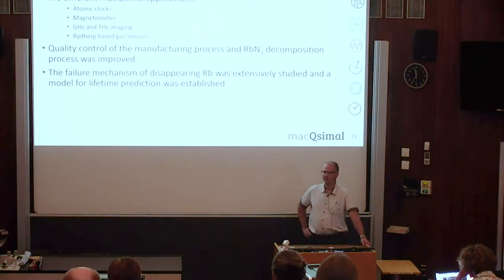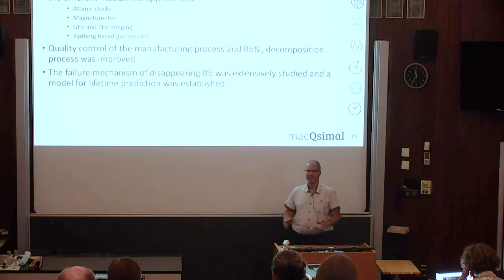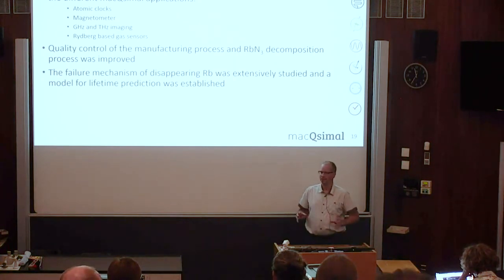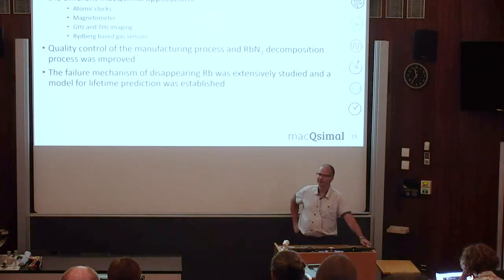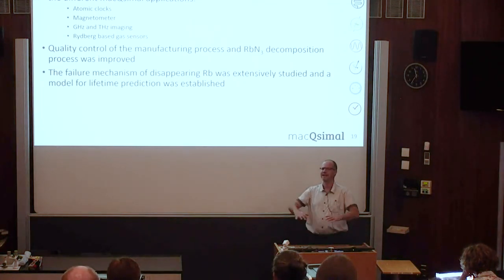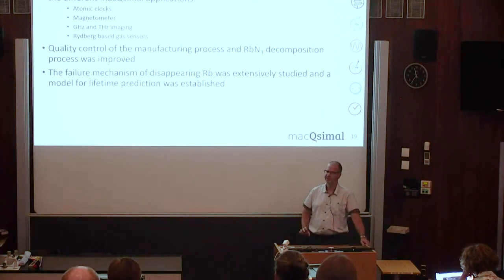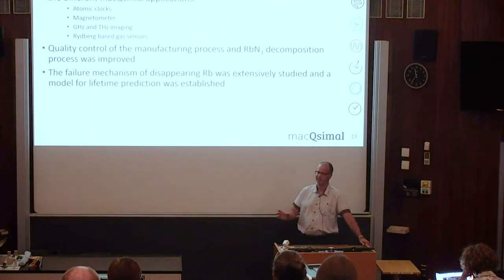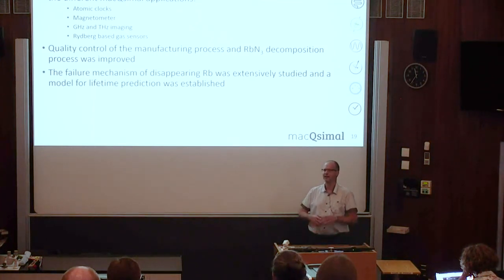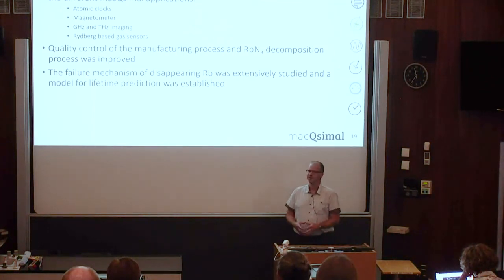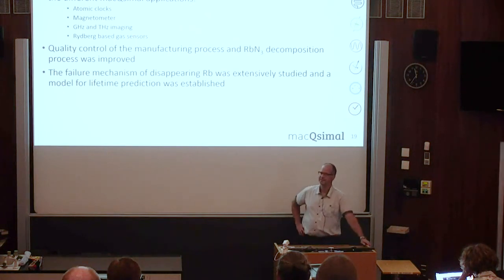And the advantage of a dot is also that you can, in principle, design many small dots or a few bigger dots. But we have seen from the Kelvin equation that if you have a bigger drop, if you force the rubidium to take a bigger surface, the vapor pressure above this gold disk will be lower than if it would be small. So it is of interest to have very few dots, but of a certain size.